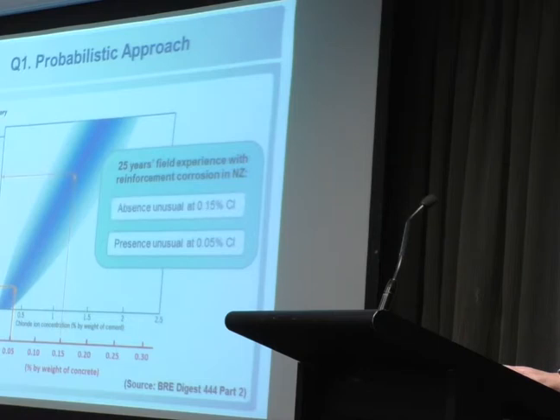The best you can do is talk about probabilities. And in Opus's field experience doing condition assessment studies, that is pretty much right. At about 0.05% chloride contamination at the reinforcement, it's unusual to see reinforcement corrosion, as that would suggest. At 0.15%, it's pretty unusual not to see reinforcement corrosion, although, as Rob highlighted, there are certainly cases where you don't. And so maybe 0.10 is a reasonable threshold to choose if you were just trying to look at the risk to existing structures. And I would emphasize that there is a difference between looking at the risk to existing structures and the figure you should use for design purposes, which obviously needs to be a lot more conservative.